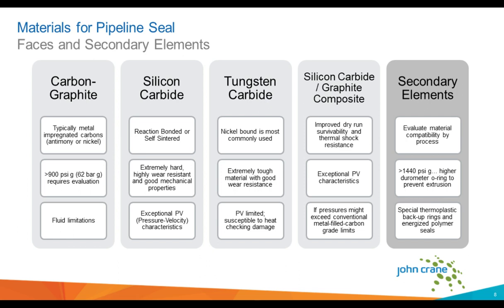Because of the very robust nature of the material, it's recommended to use a more robust drive design for seal rings manufactured of these materials, and that helps to avoid potential hang-up that can occur, especially when these harder materials contact comparatively softer metal components such as retainers and other adaptive hardware components in the seal. The limitation of silicon carbide is that it's prone to thermal shock. In other words, heating up and rapid cooling can actually result in failure or fracture.